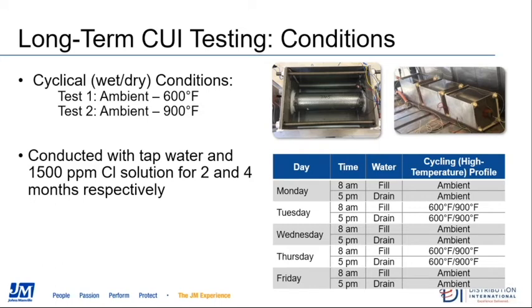What you can see with the graphics there, the graphic on the left is an overhead shot of the testing vat. What you'll see is the pipe insulated with the metal jacket. What you won't see is on the underside of that, there is a hole drilled in the metal jacket. The purpose of this hole is to allow water to infiltrate the system. The picture you're going to see there on the right shows the same testing vats, this time full of liquid.